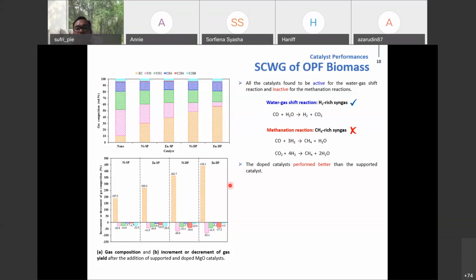Okay, another piece of information is we found out the doped catalyst... This diagram I changed into another presentation so we can see it clearly. The yield of hydrogen keeps increasing. The yield of other gases is reduced. So we can also see the doped catalysts, the nickel DP and zinc DP, perform better compared to the nickel SP and also the zinc SP. For the zinc-based catalyst, let's say we don't care about the structure, support or dope, we find out the zinc is always better than nickel. It means zinc is the active component to gasify the biomass to produce a high amount of hydrogen yield.